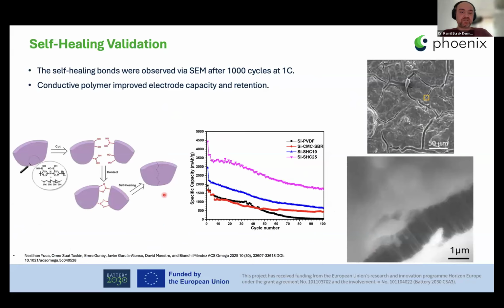In the previous project involving autonomous self-healing, we were able to establish a candidate for self-healable binders that could be an option for silicon-based batteries. We have used different binders: PVDF, very well established in lab-scale research for NMP-based slurry preparation; CMC and SBR, widely used in water-based slurry treatment; and our self-healing polymers. The results show that if we can tune the content accordingly, the benefit will be remarkable. After cycling of the cells, we could see that self-healing is also taking place, and we were able to see the interlinks between the cracked regions thanks to the self-healable polymer binders.